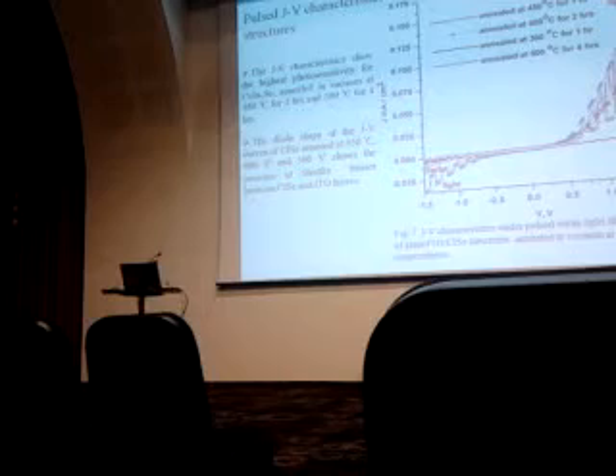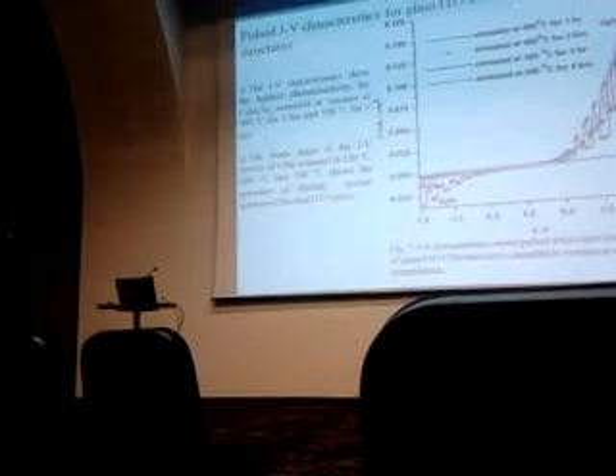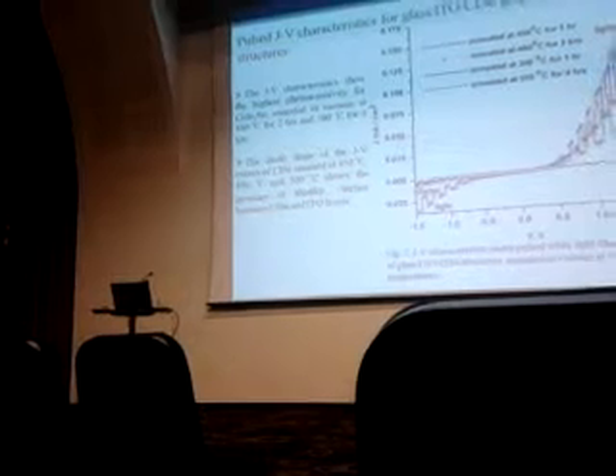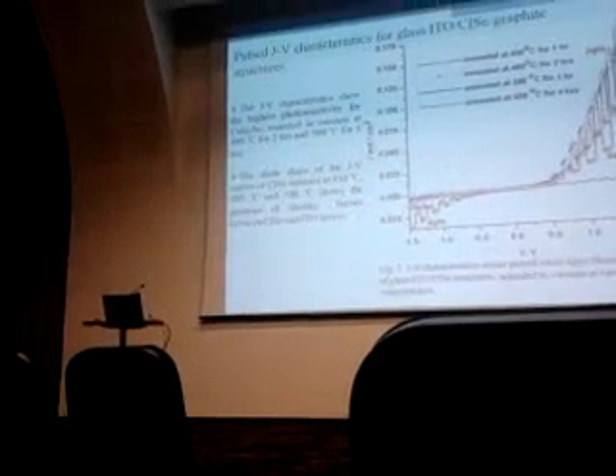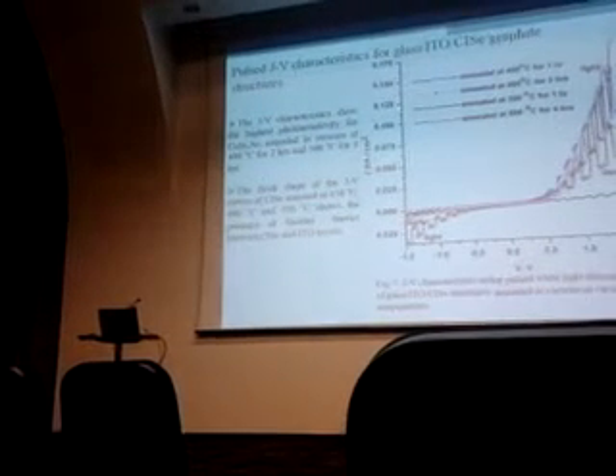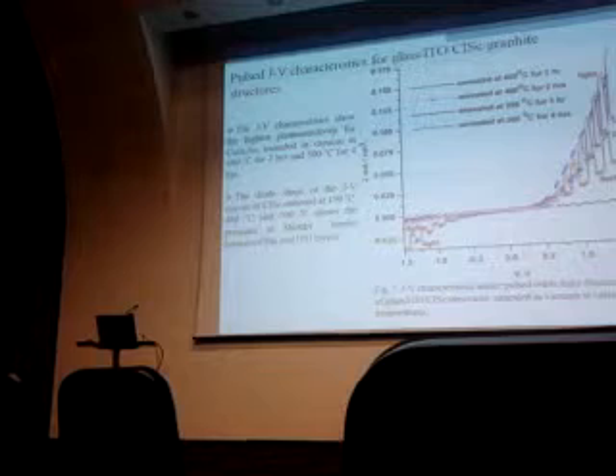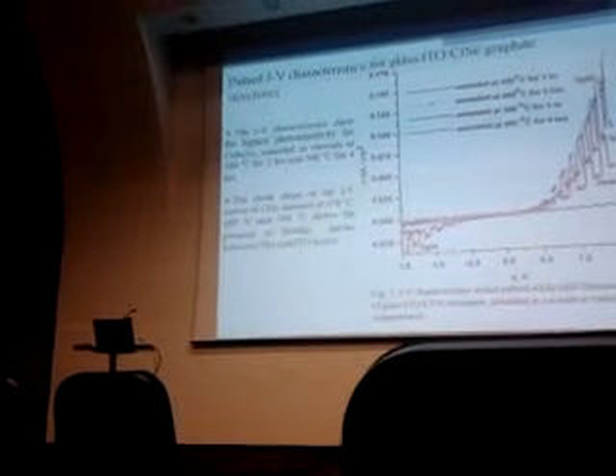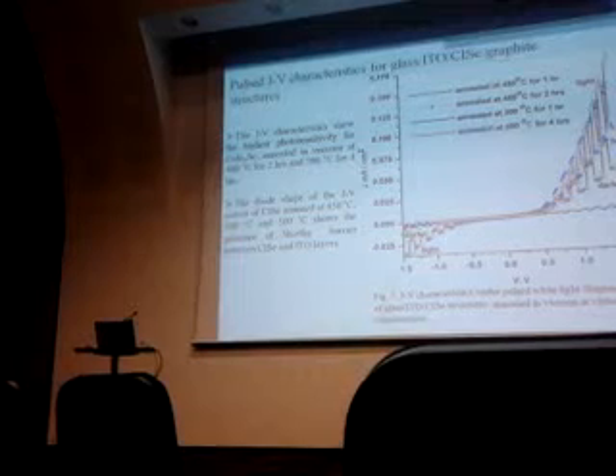Next, we also did the current-voltage characteristics of the glass/ITO/CISe structure, using graphite dots as another contact. We are investigating copper indium 3 selenium 5 as a photo absorber material only - it is not a complete solar cell. Therefore, this graph is taken with ITO, copper indium 3 selenium 5, and graphite structure.